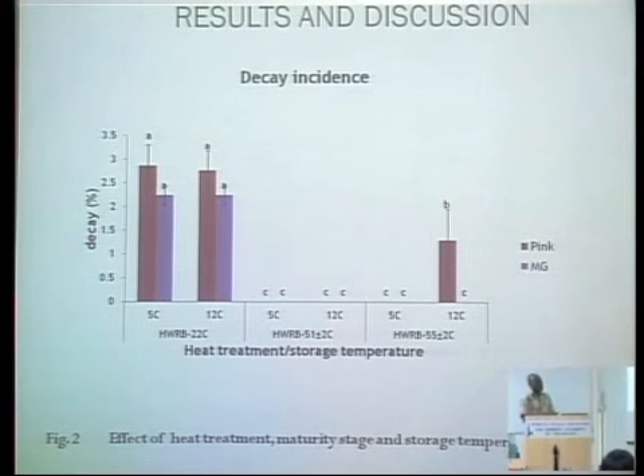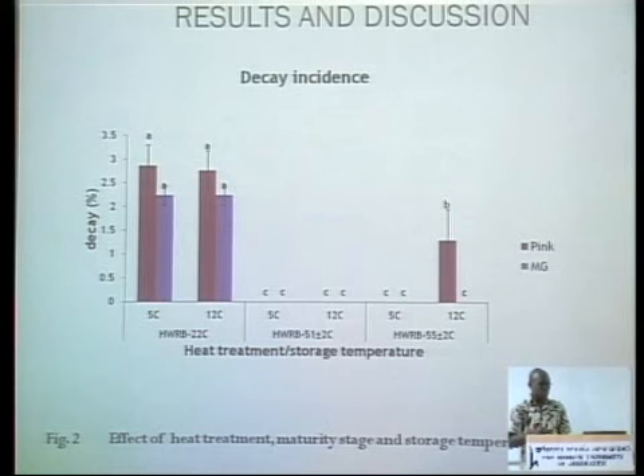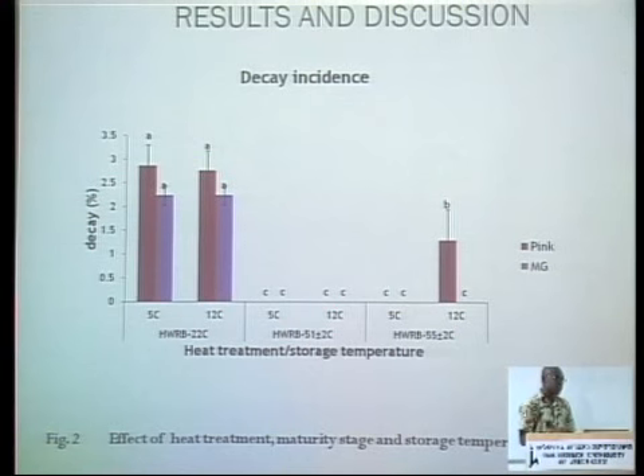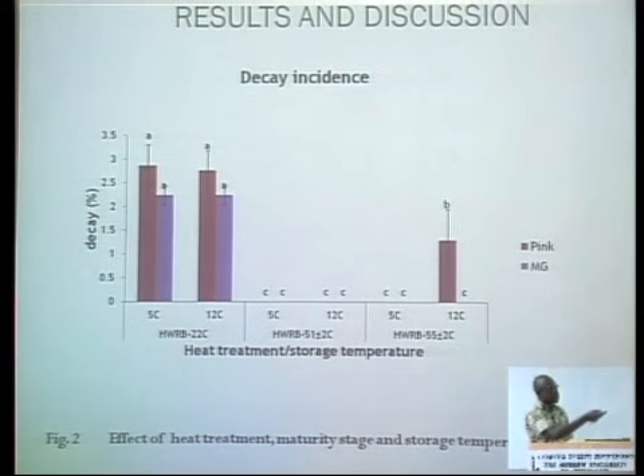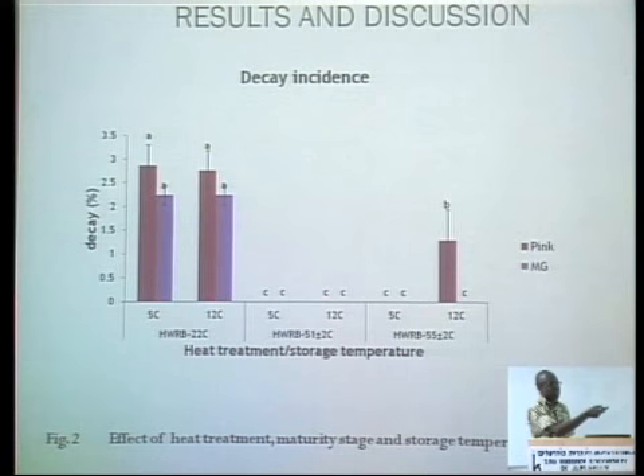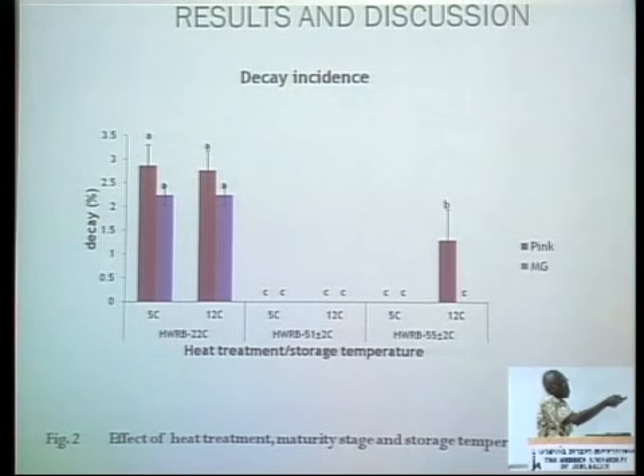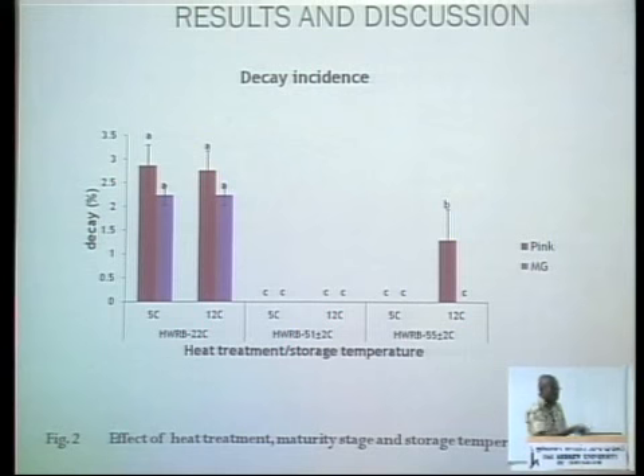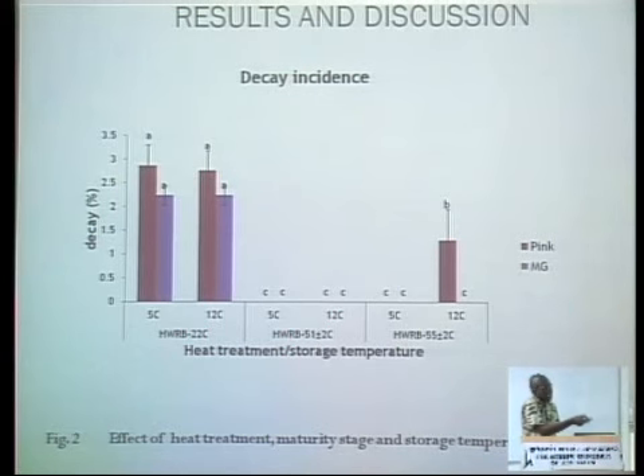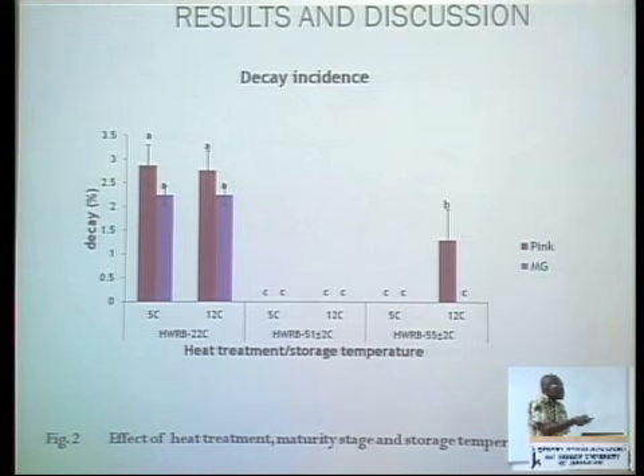And literature has shown that in the skin of the fruit, or the peel, there is a pathogenesis-related protein like chitinase, which when induced by thermal stress can help to prevent pathogen attack. So we think that the gene responsible for producing this protein was more expressed in the mature green than in the pink. And so the heat treatment would have caused more expression of that gene in the peel of the mature green than in the pink. Yes.